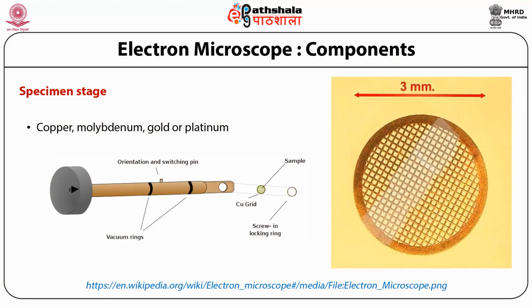Specimen stage. This is made up of copper, molybdenum, or gold or platinum, and as you can see in these two pictures, on the right hand side we see the grid on which the sample is kept. The sample has to be ultra thin. It should be around 100 nanometers in width so that it can be properly visualized and electrons can pass through it easily. A thicker sample will have a problem in terms of resolution because most of the electrons might get trapped inside the sample and would provide a dark black image instead of a high resolution image.